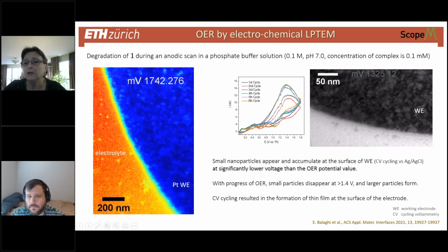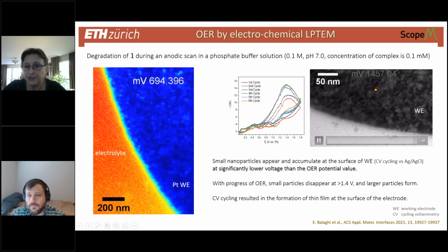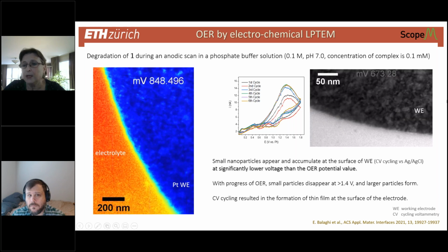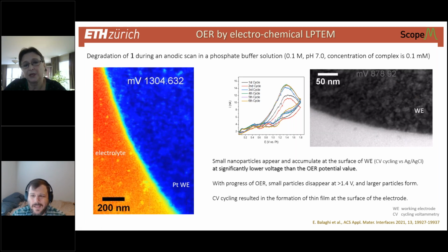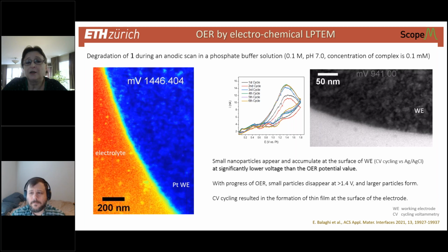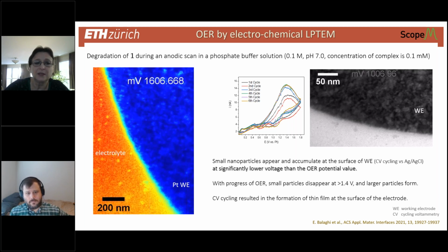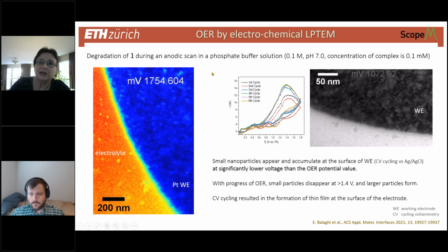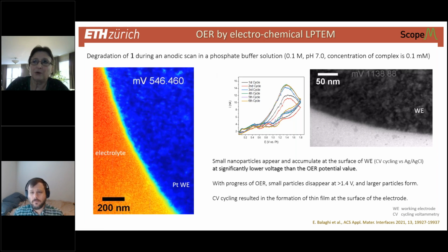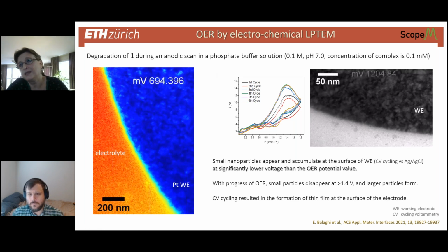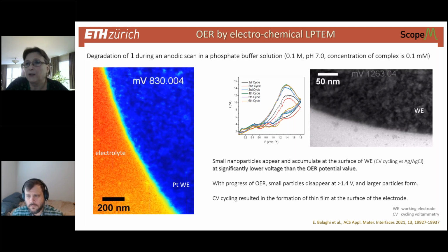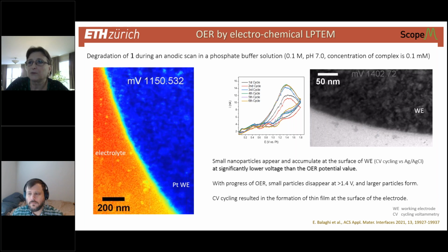Immediately, nanoparticles form at the surface of the electrode, and you see them. You can perceive them already here. Amorphous material doesn't have so much of it. You cannot speak about any epitaxy, of course, with amorphous material. And copper is polycrystalline copper, not single crystallite copper. I wouldn't expect any match of copper or copper oxide to the platinum crystalline facets, because the lattice parameters for those species are quite different.